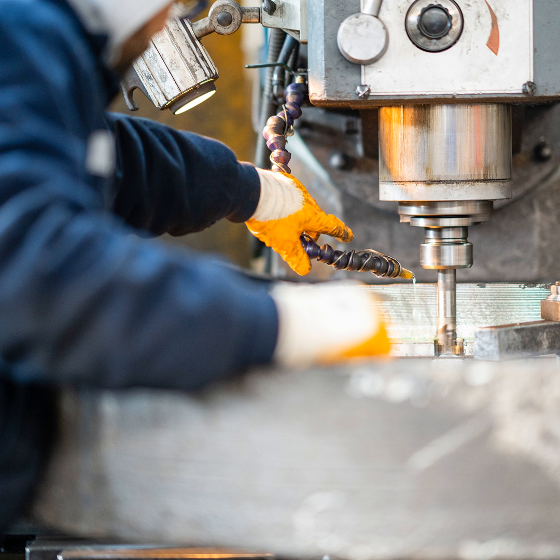Because of the finer grain size, we're allowed to have more precise cutting edges, which is very, very important when cutting ISO-S materials. We don't want to overcompensate and have large edge rounding to the corners. So with the fine grain structure, this allows us to have very sharp, homogeneous cutting edges. This process is highly controlled. It's not batch manufactured. It's done one at a time, and it's measured. Each tool is measured and qualified to the specific requirements, ensuring maximal and predictable tool wear.